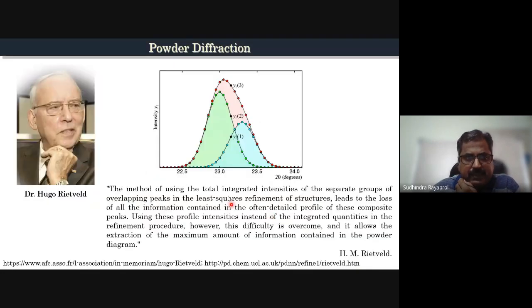But thanks to a person known as Hugo Rietveld, he was the one who actually solved this problem of peak overlap. So let's say, for example, you have one peak which you can see by the naked eye in a diffraction pattern, but it actually is a combination of 2 peaks. It's a resultant peak which gives you the single peak. What Rietveld said was that the method of using the total integrated intensities of the separate groups of overlapping peaks in the least squares refinement method leads to loss of all the information contained in the often detailed profile of these composite peaks.